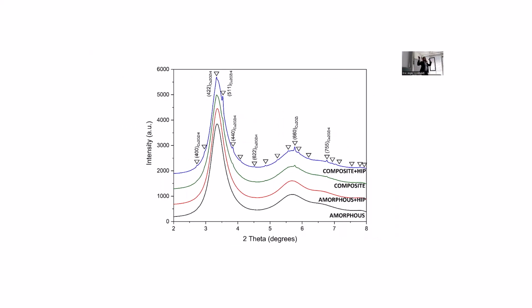We use this low temperature, very high pressure to get the glass densified. And of course, the question: does it crystallize? No, it does not. Here, the sample with the optimized strategy is the amorphous one. The upper one is the one after the heat process.